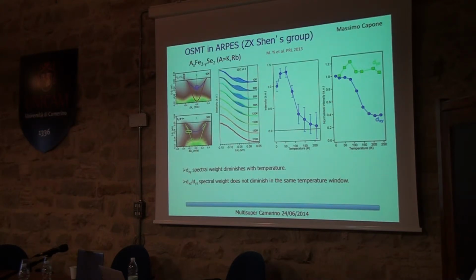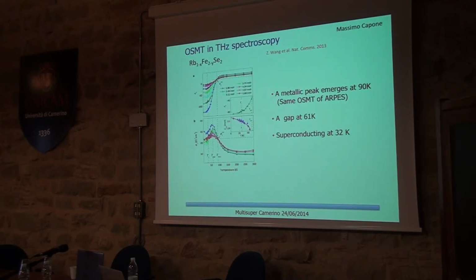These are more direct experiments that I will very rapidly talk about. I'm not even talking about... There are measurements on these layered intercalated materials where there is an orbital selective Mott transition in photoemission. We see that the XY weight disappears at some temperature. This is essentially confirmed by terahertz spectroscopy, where you clearly see a signal which mirrors precisely the weight of the XY. That's in Joachim Deisenhofer's group.